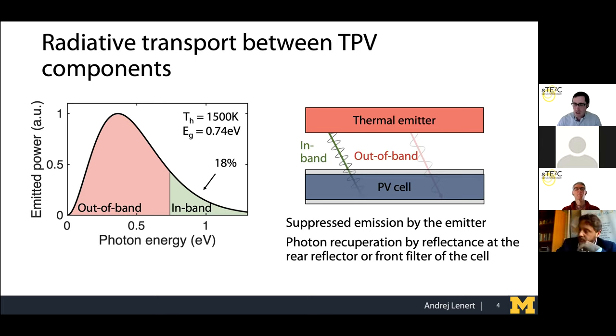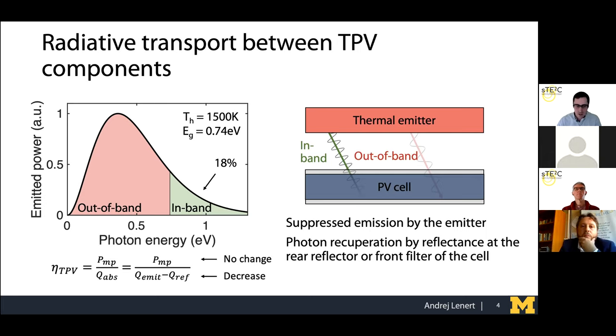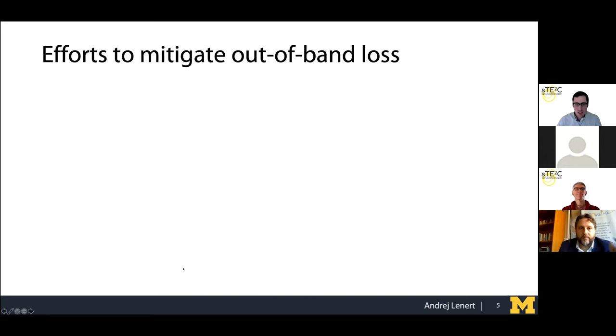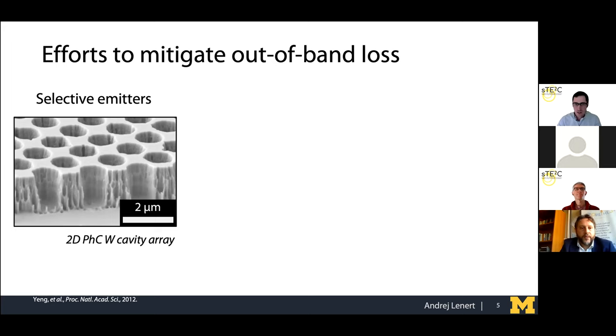And in practice, this approach of reflection can be easier to achieve because photonic structures at high temperatures are very challenging to engineer. So the idea is getting to high efficiencies by keeping the same power generation, but decreasing the denominator, and the denominator describes the amount of absorbed power, which can either be done through decreased emission or through increased reflection.